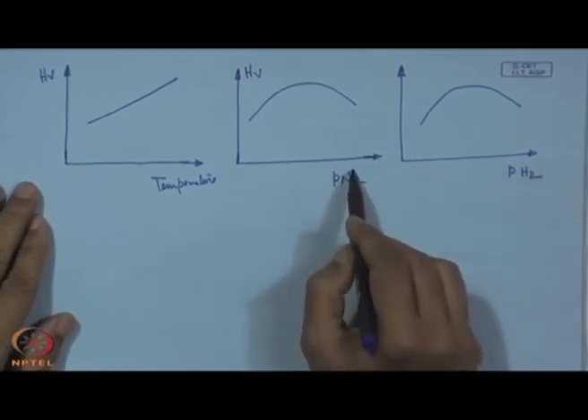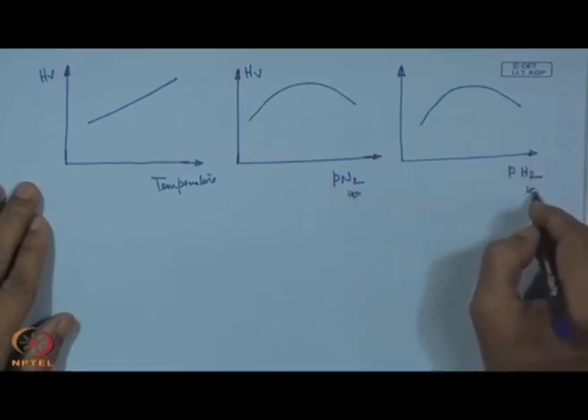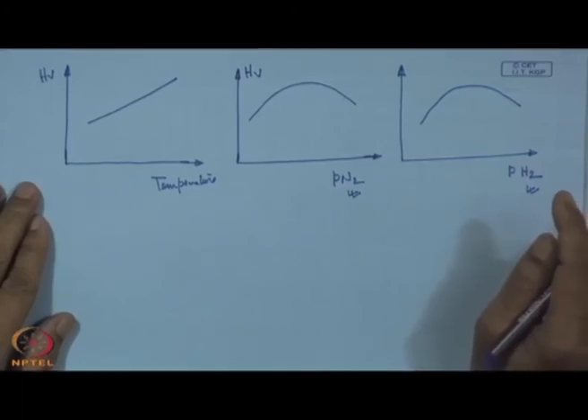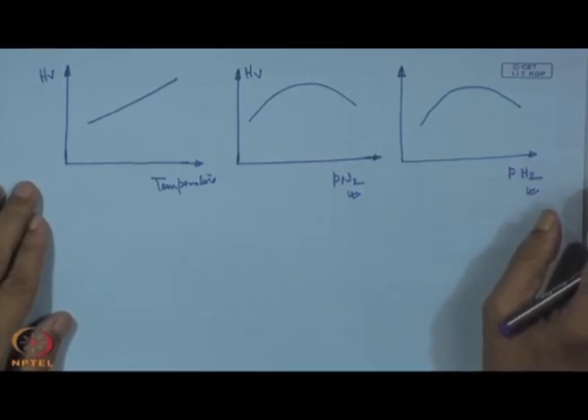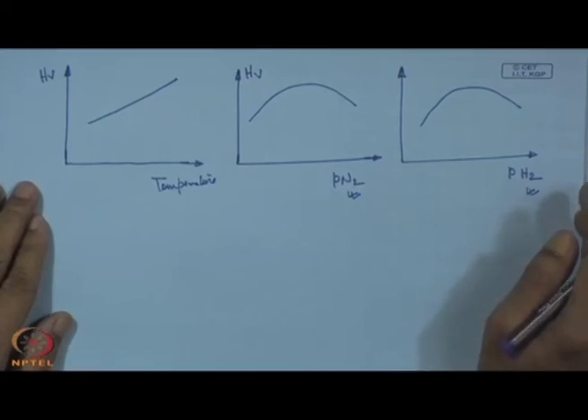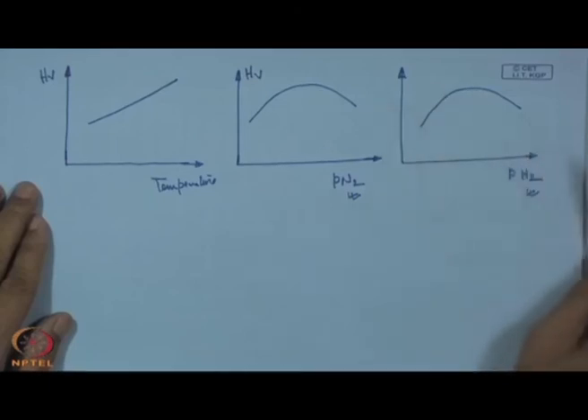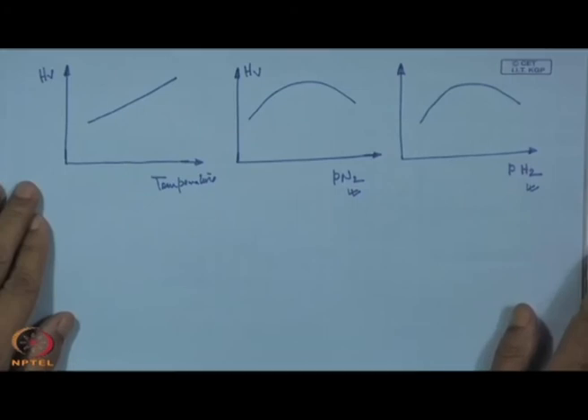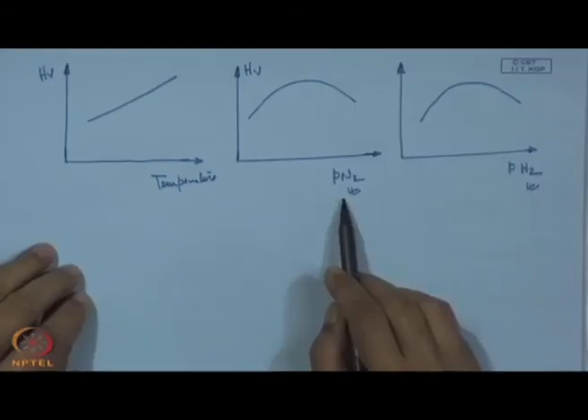But if we increase this value of nitrogen or hydrogen excessively, then we can also have a soot-like structure, which has less compaction and less hardness. In that case we have what we call dust formation, and it is a homogeneous reaction which can take place in the gaseous phase. As a result, this is not exactly happening on the substrate surface, and the structure is not so densified and this will be translated into a low value of hardness. So, we can summarize that with excessive nitrogen and excessive hydrogen there could be a fall of the hardness.